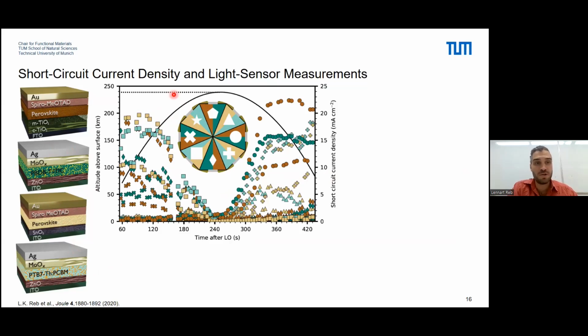We're talking about short circuit current density, meaning that every single data point that we see here is obtained from one sweep. So we basically have one measurement every 5 seconds here. And we know that the photocurrent is somehow proportional to the solar power shining onto the solar cells. So we can see here that we have different illumination conditions during the flight. But we still don't know how much sun we received.